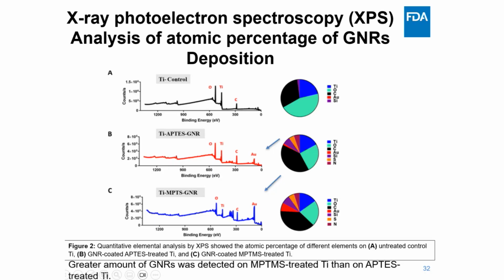So this complements our earlier SEM and EDS results, which visually showed denser coverage with MPTMS, and chemically both EDS and XPS confirmed that more gold is actually bound to the surface. So across multiple methods, we are seeing a consistent pattern. MPTMS enables stronger and more uniform GNR, or gold nanorod, attachment on titanium.